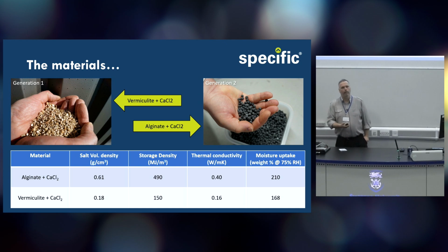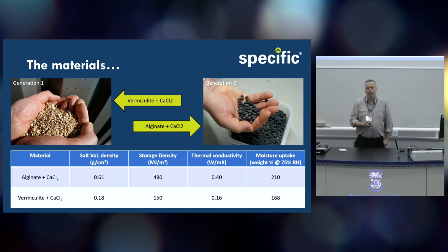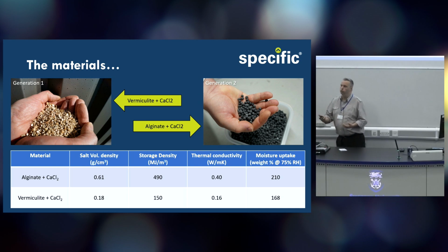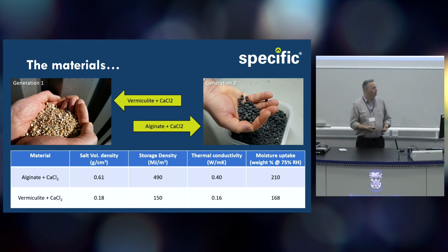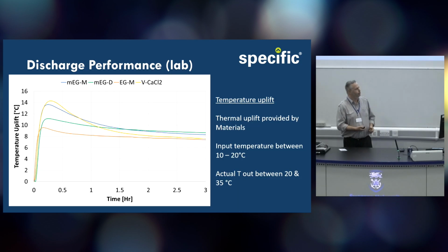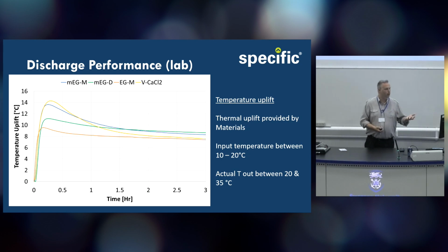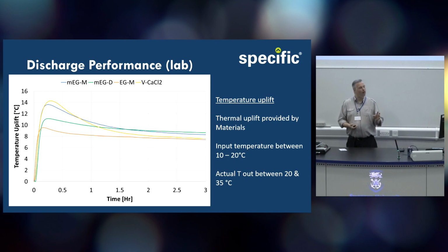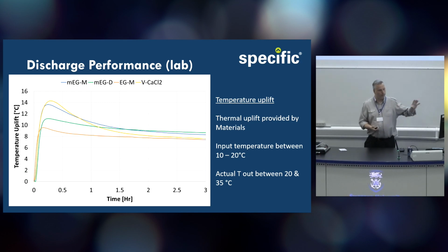So as a research group, we've looked at these materials in two different ways, through the discharge process and through the charging process. I'm here really to talk about the charging process today, which is about industrial waste heat. But what I thought was I'd just demonstrate to you that actually we can get some heat out of these materials. So this is a graph which details in about 40 grams worth of material up to about 400 grams of material. The profile is pretty much the same.